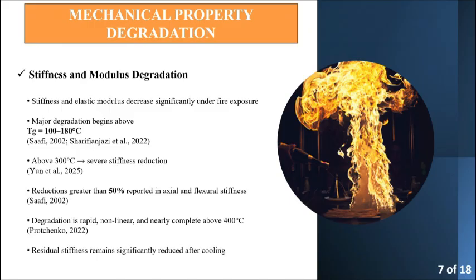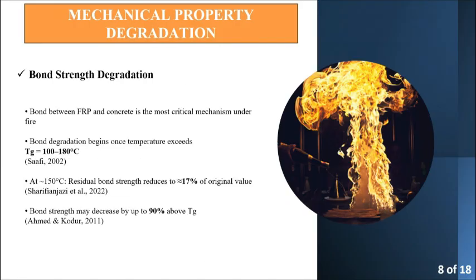So because of this stiffness loss, the structures may experience larger deflection. For sure, it will reduce the stability and increase the risk of failure or collapse. So we can conclude, based on this slide, that the fire exposure significantly reduced the stiffness and rigidity of FRP reinforcement members, making them more vulnerable to deformation and instability.